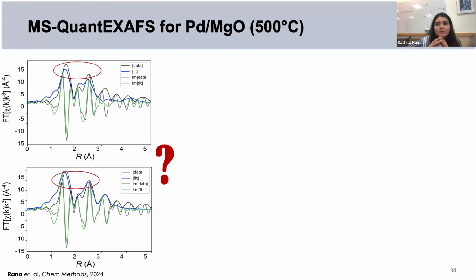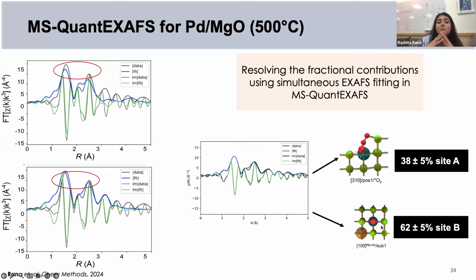So we found that we went from a palladium surface site that was going subsurface, and at 500, some of those sites were already subsurface, which is why we had a fractional contribution of both the surface site and the subsurface site of palladium that resulted in a much better EXAFS fit using MS-QuantEXAFS. So we were able to fractionally resolve this and then validate this further by using the data from our DFT